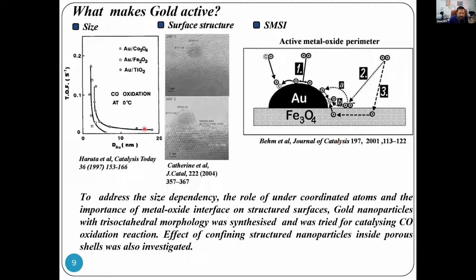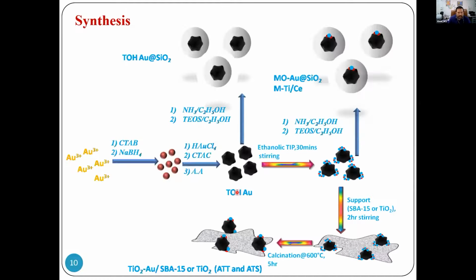So the bottom line is, if you want to have a catalytically active gold, then the size has to be less than 10 nanometers. Under what circumstances gold becomes catalytically active is the question that we wanted to understand. To do that, we looked at specific faceted gold nanoparticles. These are called trisoctahedral nanoparticles of gold, which are high index faceted gold nanoparticles, which carry a lot of undercoordinated sites, a lot of step atoms present on the surface.